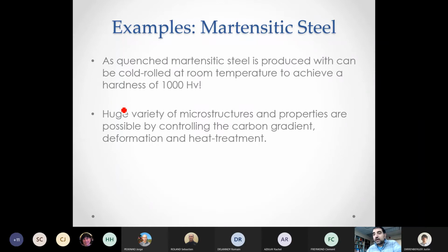And we were able to actually make martensitic steels with up to 0.4% carbon that could be cold rolled in the as quenched state, which is quite remarkable. I'll show you in a minute, and could achieve a hardness as high as 1,000 Vickers in that way. And then by choosing our decarburizing treatment, by controlling the composition, and by choosing our deformation and subsequent heat treatments, we were able to create a very broad family of martensitic steels. And that will be the main topic I share with you today.